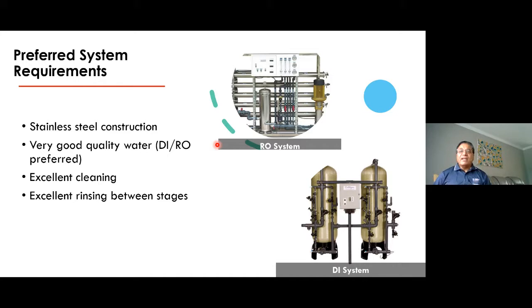Excellent cleaning. I have reinforced that during my many talks for the last several years at various associations. Excellent cleaning, excellent cleaning, excellent cleaning. There is absolutely no ifs and buts about it. Remember, as I mentioned, in the iron phosphate, you have cleaner, iron phosphate. In most cases, it's the iron phosphate cleaner coater, followed by the post rinse and a seal. Same thing, zinc phosphate, you have cleaner, zinc phosphate and the final seal. Both iron and zinc phosphate are strong acids, zirconium is a weaker acid. That's why it does not etch enough.